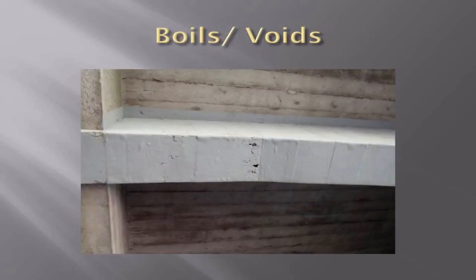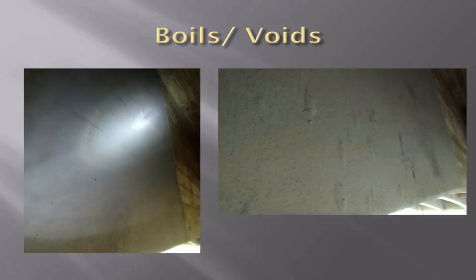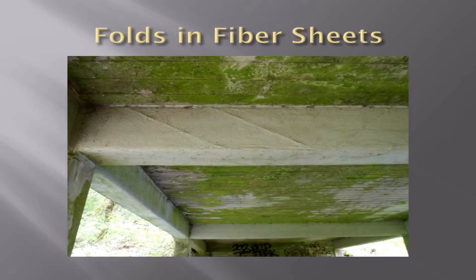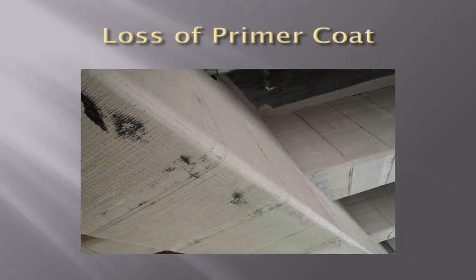Boils and voids. Here's some moderate to major boils and voids. This is probably one of the worst ones that I look at for voids on the edges. Here's kind of more common what you're going to see. There's a lot of boils and voids out there. Folds in fiber sheeting, as mentioned earlier. Anytime you have a fold or kink, it's not good. Loss of primer coat. It seems like it's not a big deal, but the primer coat does have a purpose. It's protecting that carbon fiber from UV degradation, alkali attack. So it's important to at least note.